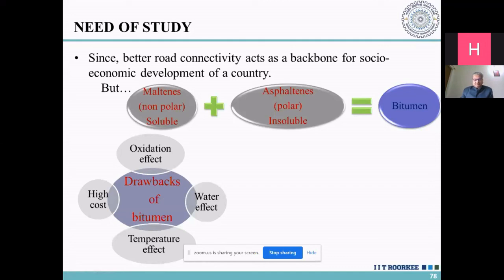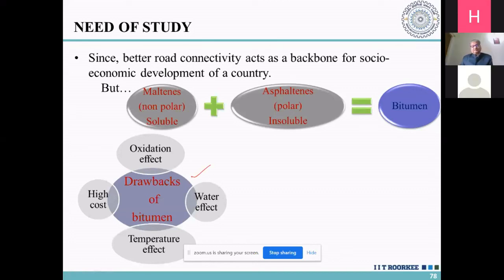But at the same time, there are drawbacks for bitumen also. First is the oxidation effect. Just like a human being, aging also takes place for bitumen, which starts from the time when it is mixed with the aggregate: short-term aging, then long-term aging. Sometimes it has an affinity towards water, so it leaves the aggregate and goes towards the water. Cost is high, around 50 rupees per kg.